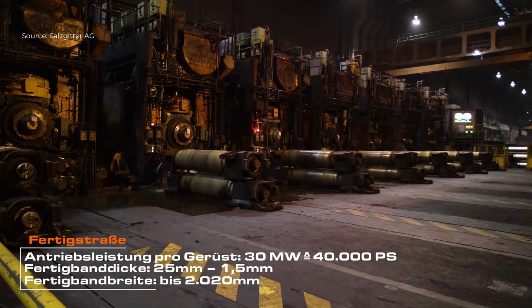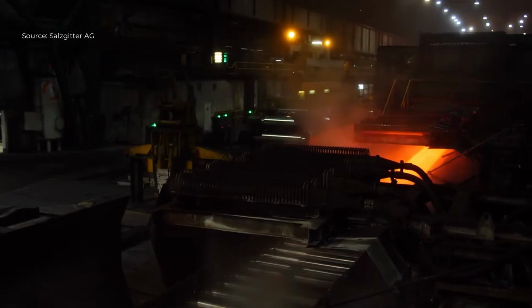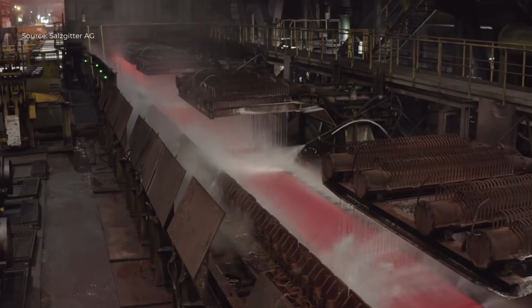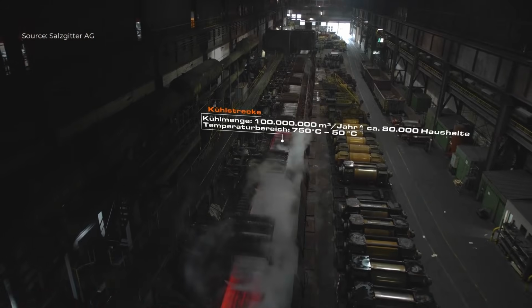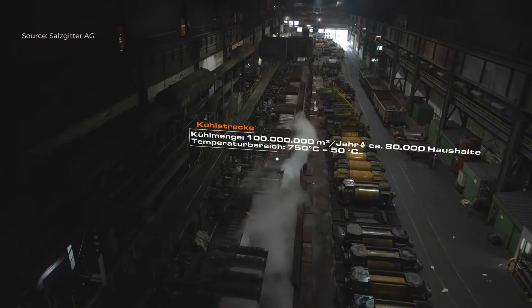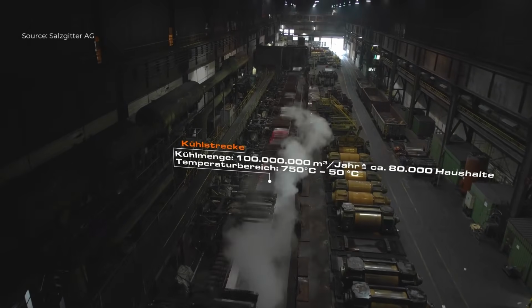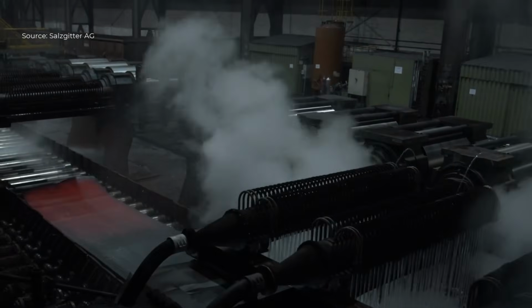The hot strip then passes through the cooling section, where controlled water cooling reduces its temperature from about 750 degrees Celsius down to 50 degrees Celsius. The cooling system handles approximately 100 million cubic meters of water per year, ensuring uniform mechanical properties along the entire length.